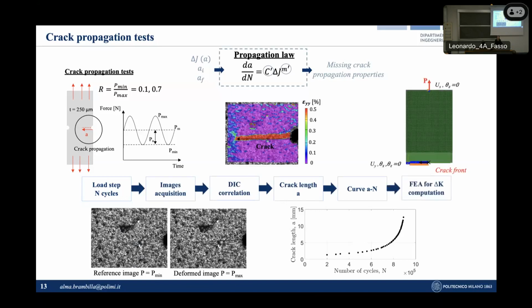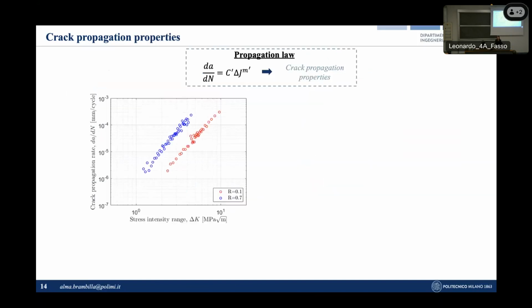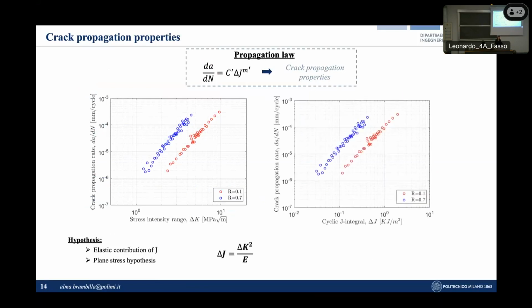Then for each one of the experimental crack lengths, a finite element simulation was performed in Abaqus in order to compute the stress intensity factor range. So the result of all this procedure was the evolution of the crack growth rate as a function of the stress intensity factor range. Then, as previously explained, the stress intensity factor range was replaced by the cyclic J integral by exploiting the relation between these two parameters under the assumption of elastic loading in a plane stress condition, which is reasonable in the case of crack propagation tests since the small-scale yielding condition was always respected.